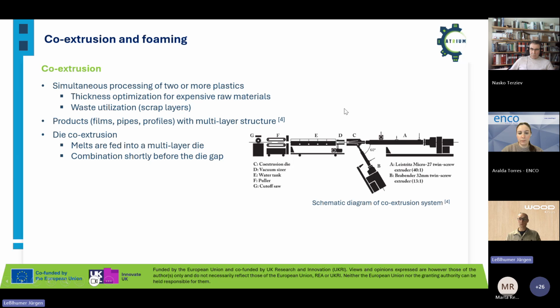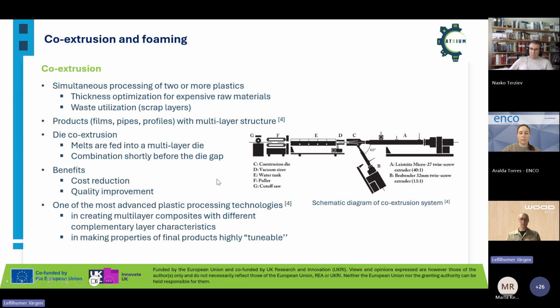And in our case, we do co-extrusion, which you can see here, a schematic picture on the slide. And during this die co-extrusion, the melts are fed into a multi-layer die, and then the different melts are combined shortly before the die gap. And after the die, the material expands, and then there is the calibration and cooling step. And the big benefits are the cost reduction, and also you can improve the quality of the profile. And that's the main reason why it's one of the most advanced processing technologies in creating multi-layer composites with different complementary layers and characteristics. And we also have the option to tune the final product properties.